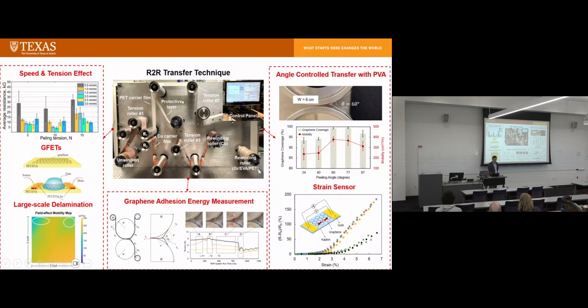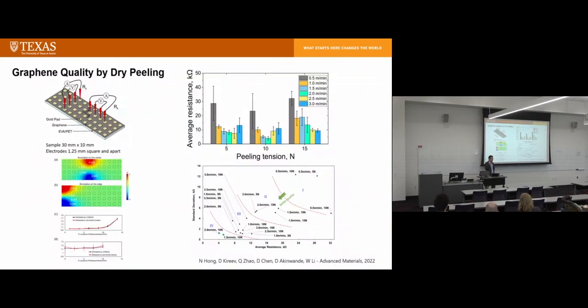We studied the speed and tension effect, and then we also looked for characteristics of the graphene, and then we did large scale 3 inch by 3 inch graphene peel, and we also studied the adhesion energy effect and also controlled angle effects for graphene transfer. And then after that, we are looking for applications for graphene.